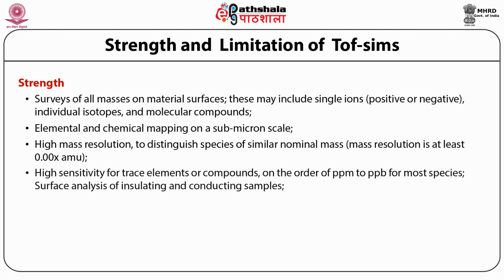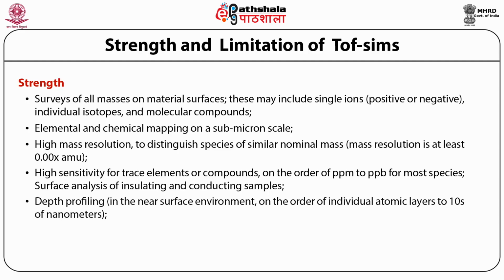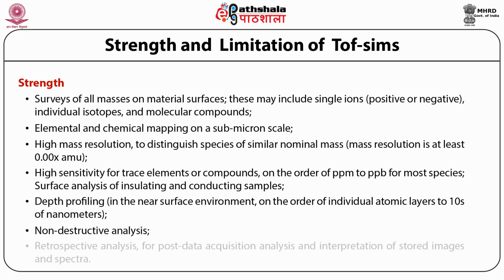High sensitivity for trace elements or compounds on the order of ppm to ppb for most species is possible. Surface analysis of insulating and conducting samples can be done. Depth profiling, that is, in the near surface environment, on the order of individual atomic layers to 10s of nanometers. It is a non-destructive analysis technique. Retrospective analysis for post-data acquisition analysis and interpretation of stored images and spectra.